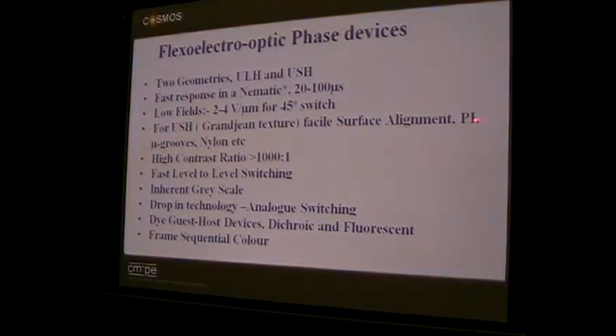I mean, in a practical device, we tend to use polyimides. Depends if we want to change, as you learned last week, the anchoring energy. But you can use rubbed nylon, nylon 66, you can use microgrooves, whichever you wish. You get a very high contrast ratio. The black state is black, and we have got up to about 3,000 in contrast ratio. You know, that's kind of unusual. You've got inherent grayscale because for a small voltage, small tilt. Bigger voltage, bigger tilt. Higher voltage, even higher tilt. It gives you an inherent grayscale, and it's easy to make 256 grayscales. You just drive that through the electronics.